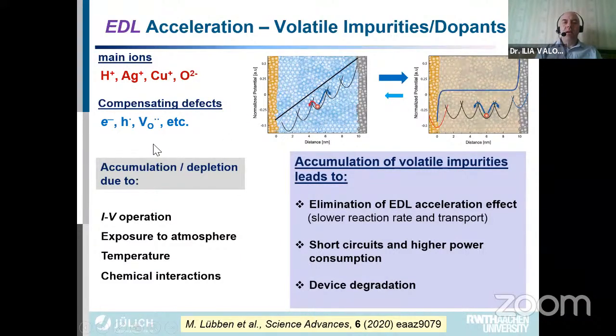This has some disadvantages. We can have accumulation or depletion of mobile charges due to the operation of the device, exposure to atmosphere, changes in temperature, and changes in the chemical composition. So you may have chemically reacting electrode and electrolyte. The accumulation of volatile impurities leads to elimination of the acceleration effect of the electrical double layer, which I told you is the field acceleration effect. It lowers the rate of transport, and it leads to short circuits and high power consumption.